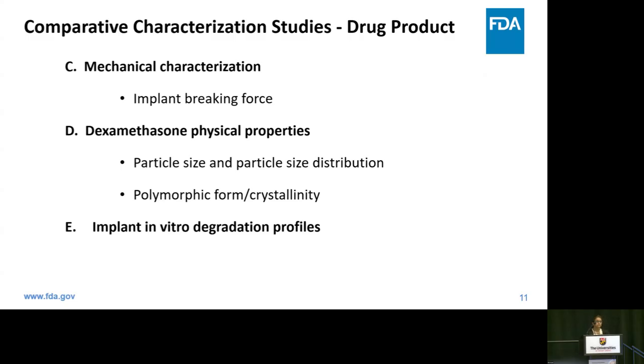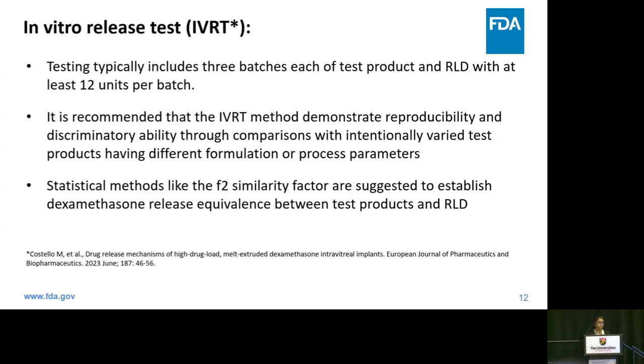So API sameness needs to be performed within the implant. For that, the recommended tests are particle size and particle size distribution, followed by polymorphic form or crystallinity evaluation. And the final one is the implant in vitro degradation profile. For the IVRT test, typically it includes 3 batches each of test product as well as RLD, with at least 12 units of every batch.